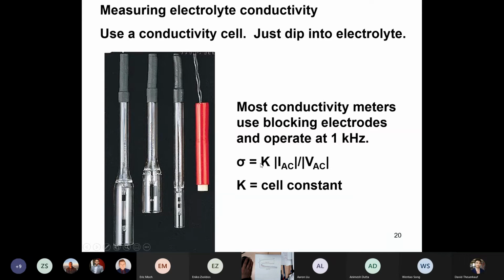So you put a solution of known conductivity into the beaker that you're dipping this into, and you can determine this proportionality constant, the cell constant, in such a simple way. So it's really simple. People may not know what blocking electrodes are. A blocking electrode means that an ion comes to the surface of the electrode and cannot be incorporated within the electrode. A counterexample is graphite with lithium ions coming nearby, because the lithium can intercalate into the graphite. A good example of a blocking electrode for lithium would be stainless steel. The lithium can't go into the stainless steel. Okay, so a conductivity cell is very simple. Now we have them. If anyone's interested in measuring electrolyte conductivity, you can do it.